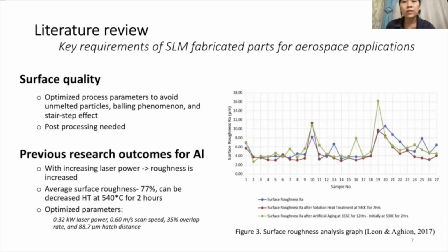0.32 kilowatt laser power, 0.6 meter per second scan speed, 35% overlap rate, and 88.7 micrometers hatch distance were determined as optimized parameters for best surface quality in as-built condition. The surface roughness can be further decreased by solution heat treatment at 540 degrees for 2 hours.